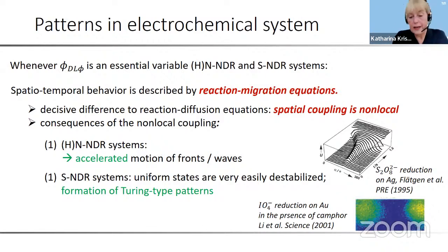The reaction migration equation has a non-local coupling, or describes a spatial non-local coupling, which means that if at some point on your originally uniform electrode you have a perturbation, this perturbation is immediately felt by a whole range of positions, adjacent positions with different strengths. Non-local means it decays in strength, but it's an entire range. And this property